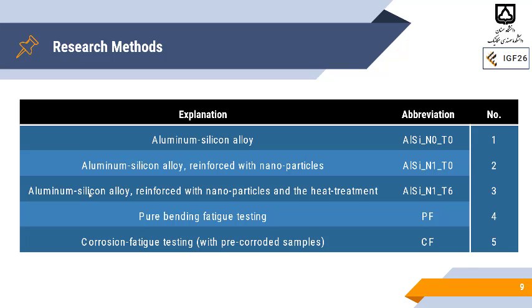So we have some explanations and abbreviation for different material that we have used. Here you can find that for aluminum silicon alloy we have AlSi_N0_T0. It means no nano we have used and no heat treatment were applied. For aluminum silicon alloys reinforced with nanoparticle, the number is N1, but without heat treatment, so we have T0. For the aluminum silicon alloy reinforced with nanoparticle and the heat treatment, both N is 1 and T is 6. It means we have used a typical T6 heat treatment. For pure bending fatigue, we have used PF, and for the corrosion fatigue testing, we have used CF abbreviations.